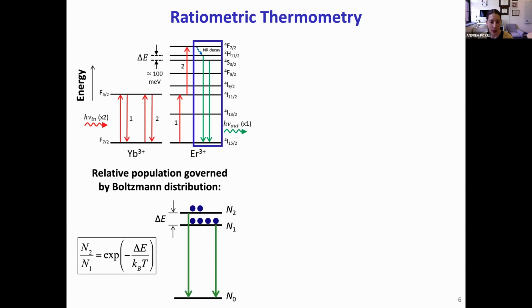What's shown here is erbium's ground state along with two closely spaced excited states from which the erbium can return to the ground state by emitting a green photon. And the key is that the relative population of these excited states is governed by Boltzmann statistics, which is fundamentally where our temperature-dependent signal comes from. The relative population of these excited states is directly related to the relative emission intensities from the two corresponding transitions.